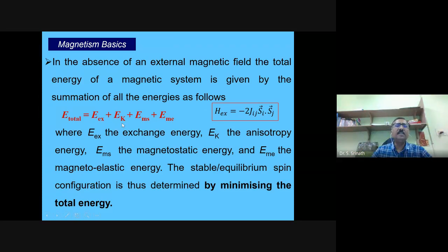So if you look at these two terms, they dictate that the spins have to be parallel along c, if I am considering the c-axis in cobalt, which has a uniaxial anisotropy. But if I consider, suppose, iron, which has a cubic anisotropy, the cubic anisotropy tells that there are 3 crystallographic axes or 6 directions, because parallel and anti-parallel. So along those 3 axes x, y, z multiplied by 2 directions, 6 directions,